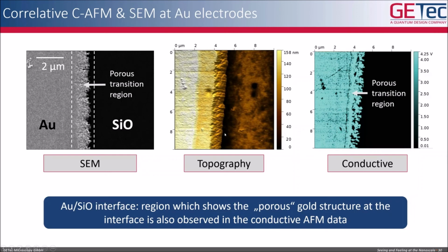But if you're working with a conductive tip, at the same time you get the conductive signal, which you can see on the right part. There you beautifully resolve the porous transition region that you also see in the SEM, in the conductive signal. This shows you that we have an extremely high resolution conductive tip. In addition, if you look at the topography, you see something added on the gold electrode, something sitting on top. In the conductive signal, this is black, which immediately tells you there's some non-conducting residue on top of your electrode that you can easily resolve in the conductive signal of your AFM scan.